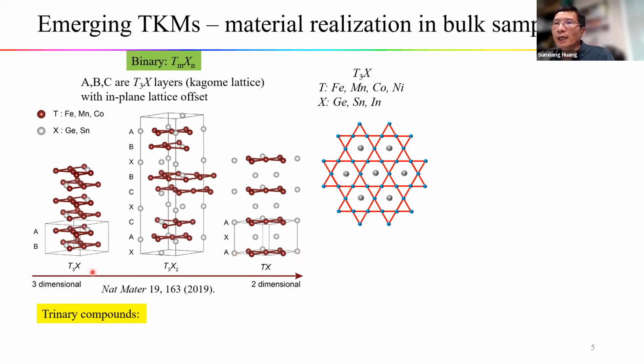For the 3-1 case, the Kagome layers are stacked together with in-plane offset. So we have the stacking like BA, BA, BA. For the 3-2, the stacking is much more complicated. The Kagome layers are first stacked in this bilayer structure, but the stacking is different. So we have this AC, this could be CB, this is like BA.